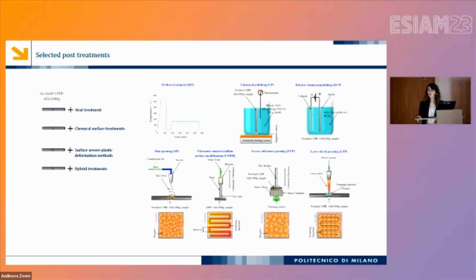especially shot peening, which is an impact-based surface treatment in which small particles are accelerated with compressed gas in order to impact the surface and induce plastic deformation. Then we have also used the ultrasonic nanocrystalline surface modification technique, which in concept is very similar to shot peening, because we always have an impact on the surface, but the impact is applied by a tungsten carbide ball that is pressed to the surface and moves along a specific route.